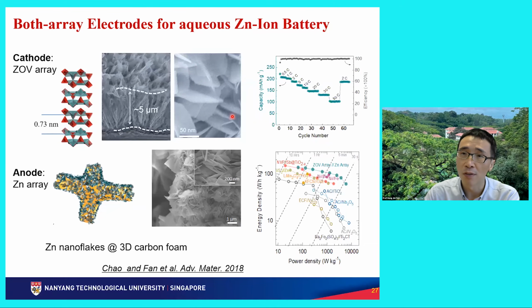So I show some examples of our research. This is also in 2018. We, again, very similar to the sodium battery before, replace the conventional powder cathode materials and conventional zinc foil, just commercial foil, with array structures. Okay, we fabricate these array structures, cathode materials and zinc, to make the materials that can charge and discharge much faster and also can cycle more stably, for a longer time. That means, let's say we can go to 50 C, we'll still have a very evident capacity here, rather than it goes to 0.